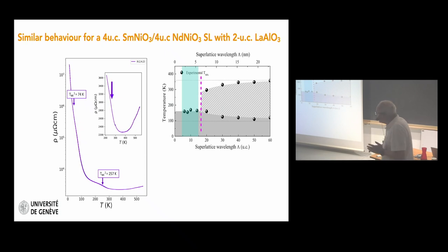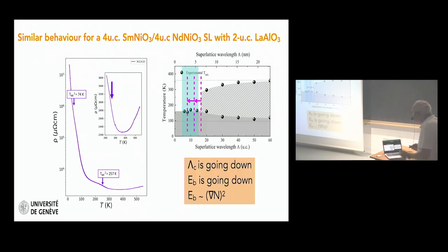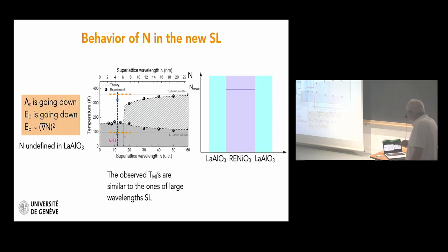Now the interesting thing is that these experiments tell us that our critical wavelength, which was 16, is now pushed to 12 and even pushed to 8. So by putting in lanthanum aluminate, the critical wavelength goes down. But if the critical wavelength goes down, it means that the phase boundary energy is going down. And in our model, it means that the gradient of n is going down. I should also say that the critical temperature of these very thin layers is very similar to that of the thick ones.